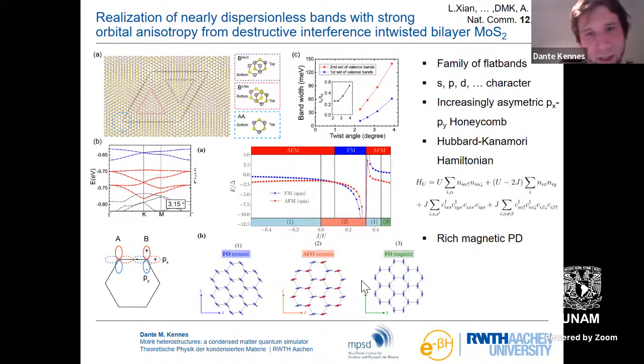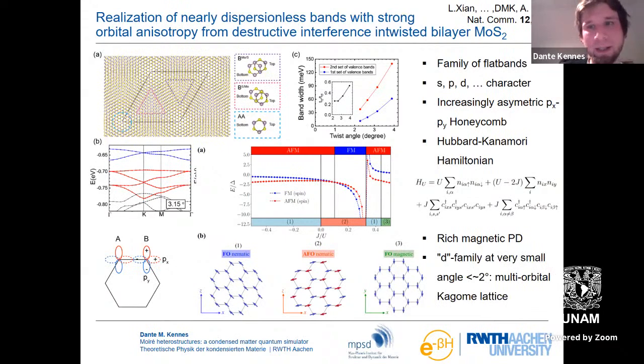For the sake of time, I'm just kind of browsing through this. But what you can see is that depending on the twist angle, you can tune the ratio of this exchange J over the value of U. And with this tuning, you can realize different spin order, so antiferromagnetic or ferromagnetic spin order. And in the orbital order, you can also get subleading orderings because you have a multi-orbital lattice. So all of this is made possible by Moiré engineering these materials.